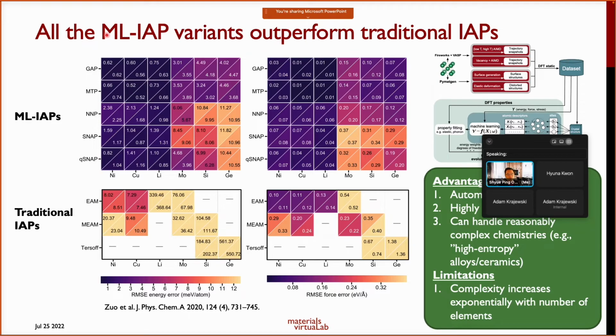all the machine learning interatomic potentials actually outperform traditional IAPs. Okay, so this is a plot of the energy and force errors. Left is energy and right is the force errors for all the different flavors, all the variants of the machine learning interatomic potentials. And these are the same results for your traditional interatomic potentials. And what you see is that the errors from the machine learning interatomic potentials are much lower than what you get from your traditional potentials like EAM and MEAM, right?